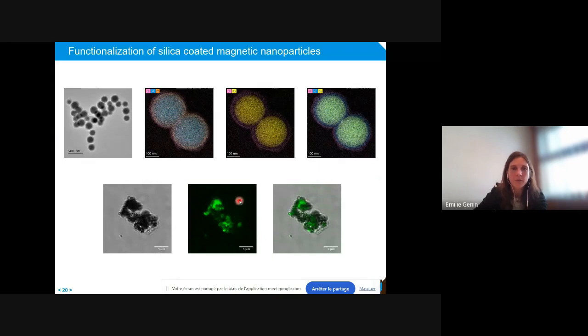To go further in the characterization and prove that the boronic acid was effectively present on the system, we did experiments with transmission electronic microscopy. Here you can see the different nanoparticles with the organic ligand surrounding them.